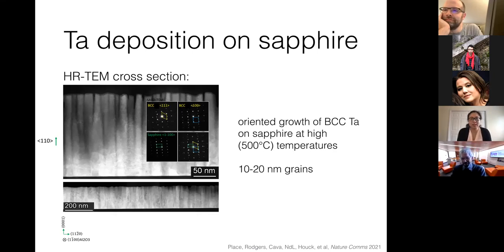Okay, the short answer is that I am not sure what components of microstructure are important or not important. From the basic perspective of whether this is a good metal, it is a terrible metal because the residual resistance ratio is very small, and it's because it has all of these grain boundaries. But what I'll point out is that it is actually very nice that this columnar growth means that it's well-oriented and epitaxial, right? So you have this nice epitaxial growth right at the boundary. And the reason that you get these columns is because there's a threefold symmetry in the underlying sapphire, so there's nothing that picks a direction. So you can either have 111 or 100 columns, and then they randomly nucleate.